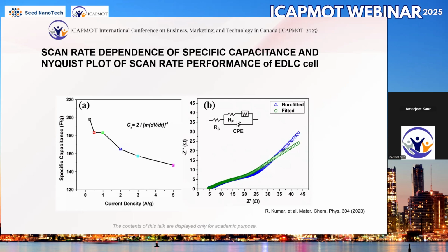So this is the equivalent circuit for this device, and you can see from the Z double prime versus Z prime plots that initially there is a very small circle here. It starts increasing, then we have a straight line curve. In this region it is purely capacitive, and then it becomes resistive. So up to 25 it is safe for us for having capacitive behavior.